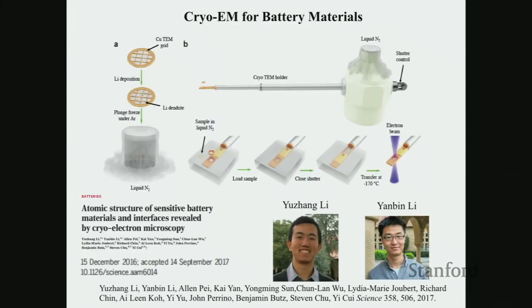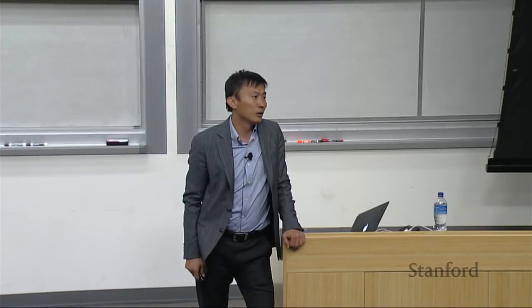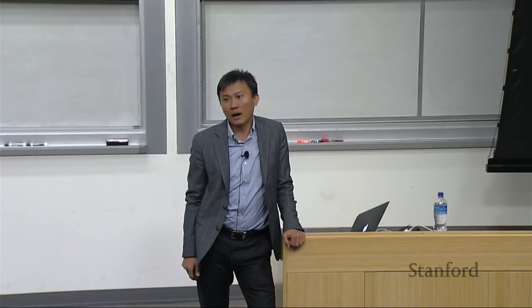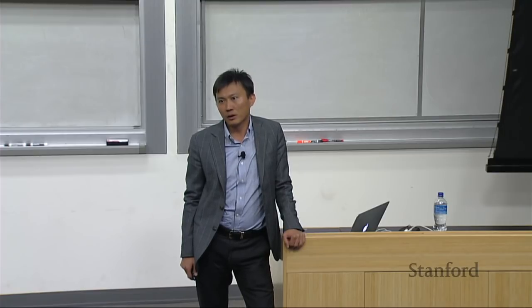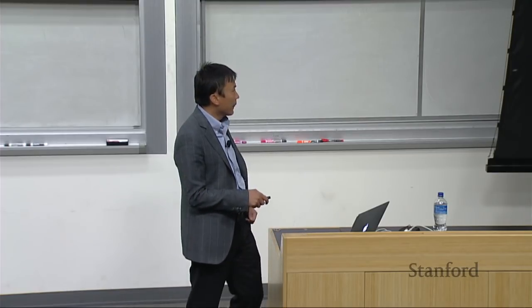Here is what they developed. We deposit, for example, metallic lithium filament onto a TEM grid and put it into liquid nitrogen without exposing it to air, and cool it down very fast. You stop your chemical reaction in liquid nitrogen, at a temperature of 77 Kelvin. And they developed a transfer technique going to the transmission electron microscope without exposing to the air, without leaving the liquid nitrogen temperature. So it took them a while to do it.